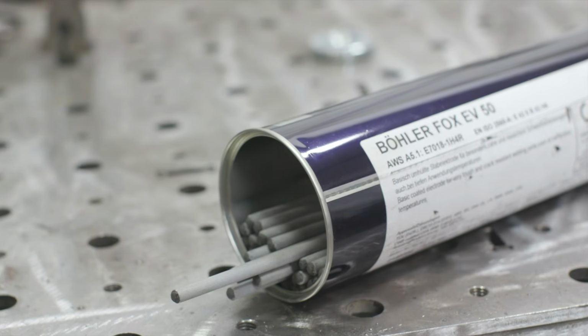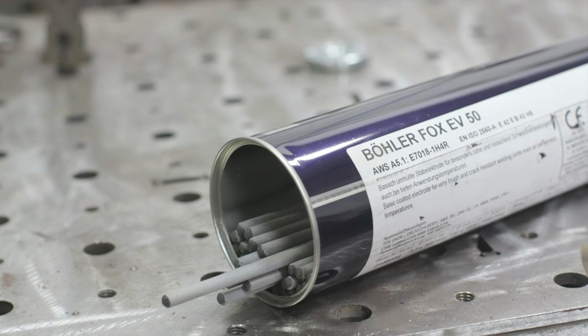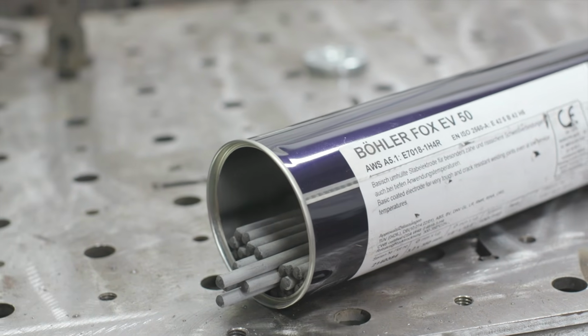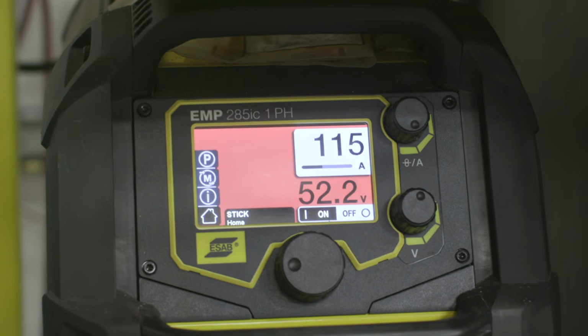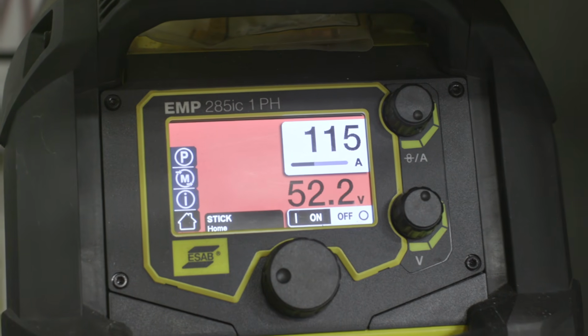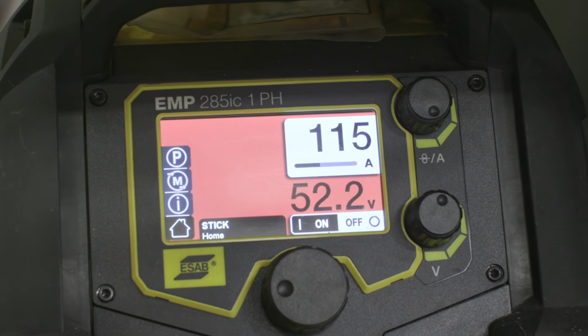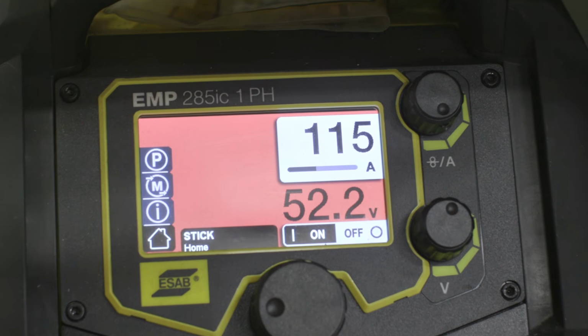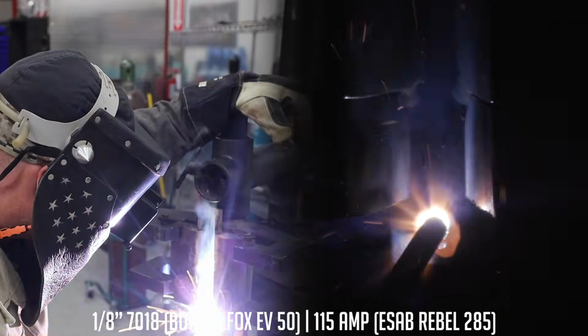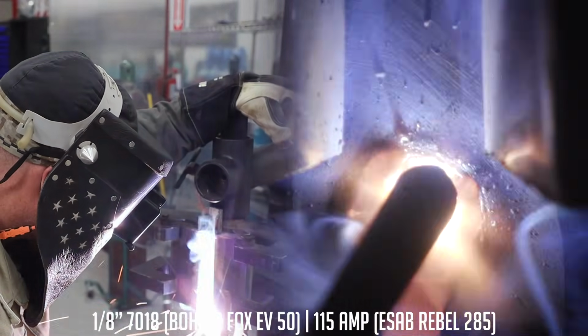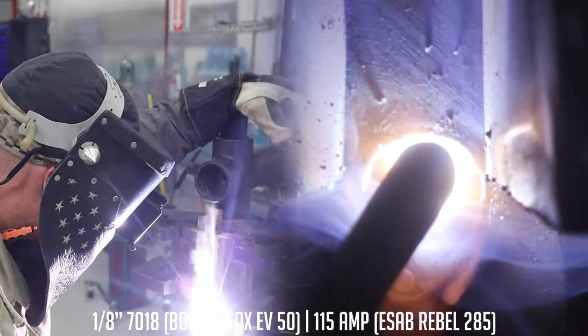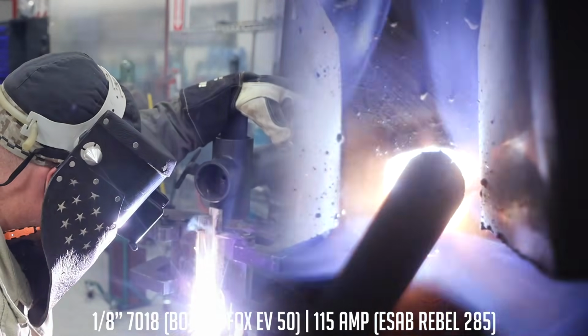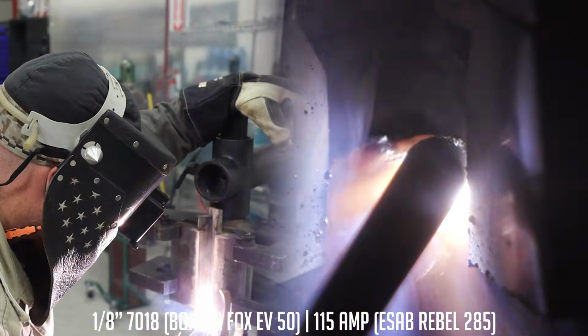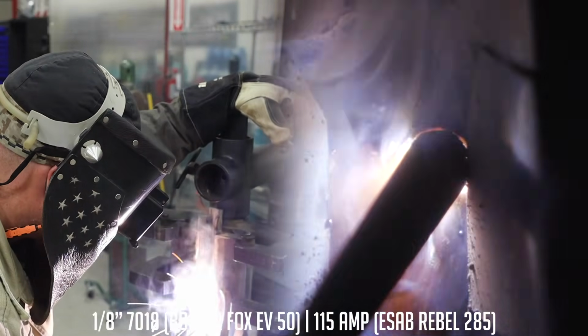So I'm running some of these Bohler Fox EV50s. It's a 7018 electrode. I'm going to be running about 115 amps on the old ESAB 285 IC, DC reverse polarity. I'm going to fire up on the bottom here on the run-on tab, move up into that weld joint and just run until I can't run anymore. I'm probably going to have to do a restart about midway, but that's not a problem. We're testing our ability to do restarts in welds. And then we'll finish that off.